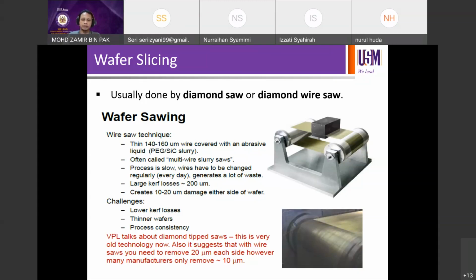So you can use that abrasive liquid, essentially liquid with abrasive. You can use PEG or silicon carbide slurry as the abrasive. In the solar industry, we call this multi-wire slurry sawing. The process is quite slow. Wires have to be changed regularly, depending on the number of wafers that we cut. Typically it's done every day, so it generates a lot of waste. We have large kerf losses, about 200 micron.